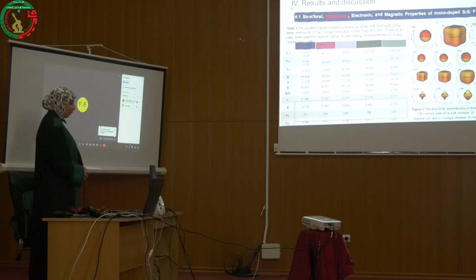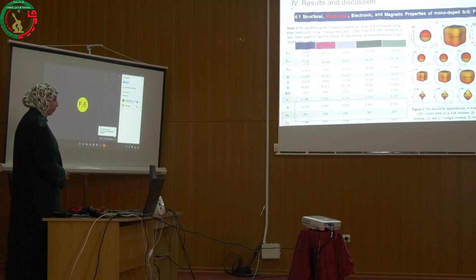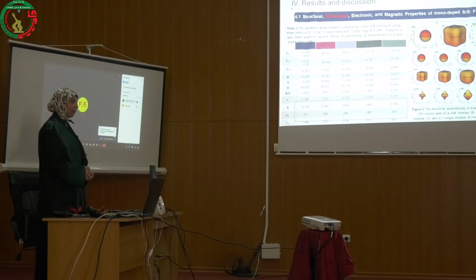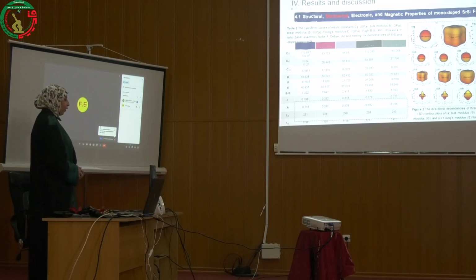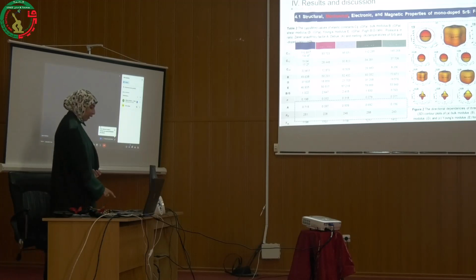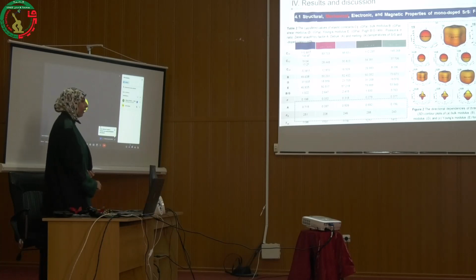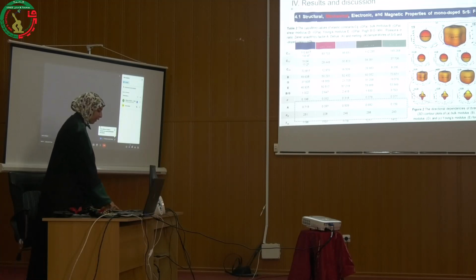Also, we looked intensively into the anisotropy of our compounds by plotting their directional dependencies for the bulk, shear, and Young's moduli. The bulk modulus shows a perfect spherical shape, indicating its isotropy, whereas the shear and Young's moduli deviate from the spherical shape, indicating their anisotropy, which became harder with increasing concentration.